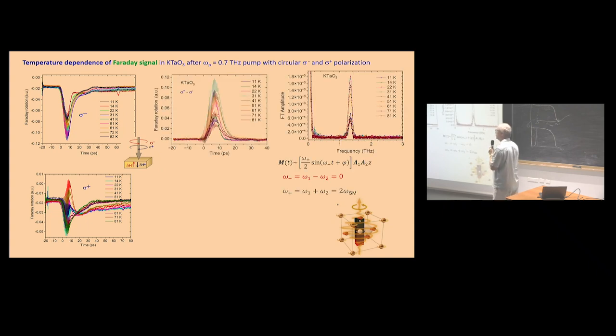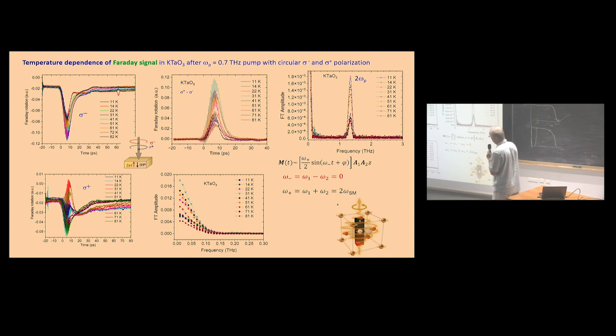So usually, to remove some effects of non-magnetic contribution to Faraday rotation, people calculate sigma plus minus sigma minus, and so we obtain such Faraday rotation, independent of temperature, and the Fourier transform gives us again a peak at 2 times the pumping frequency. I forgot to mention, pumping is at 0.7 terahertz. And this is again the electro-optic Kerr effect, but here we have an increase of amplitude, plotted better here at low frequencies, and we see an increase of intensity on cooling when we come to resonance with the soft phonon.